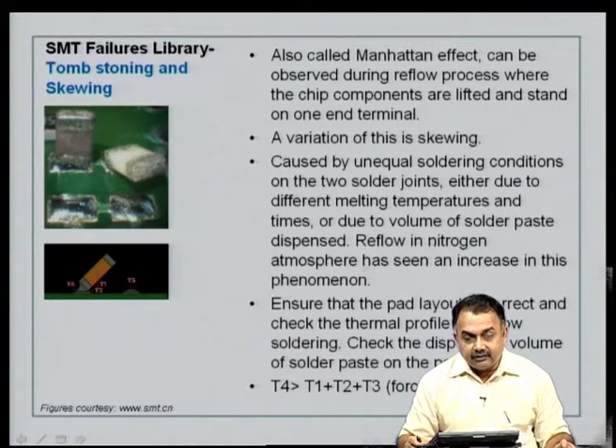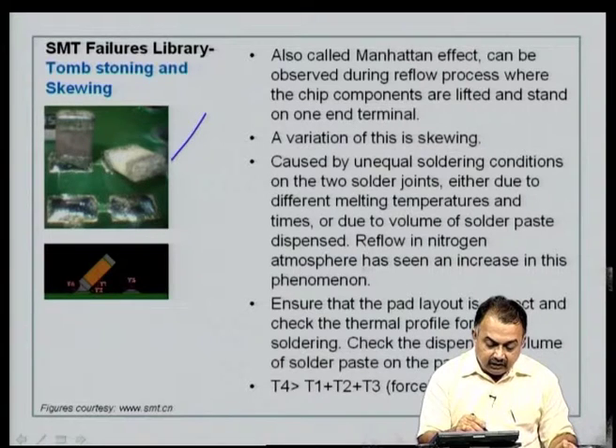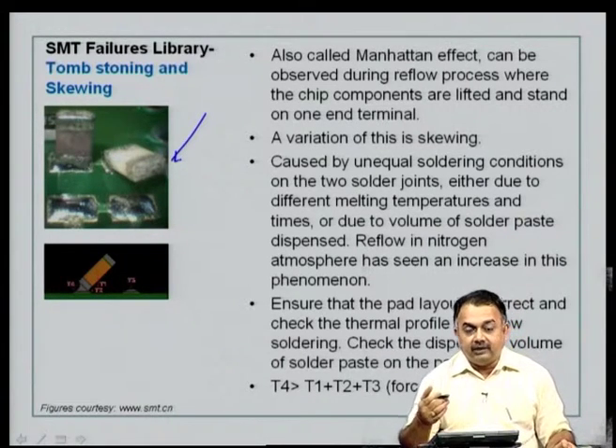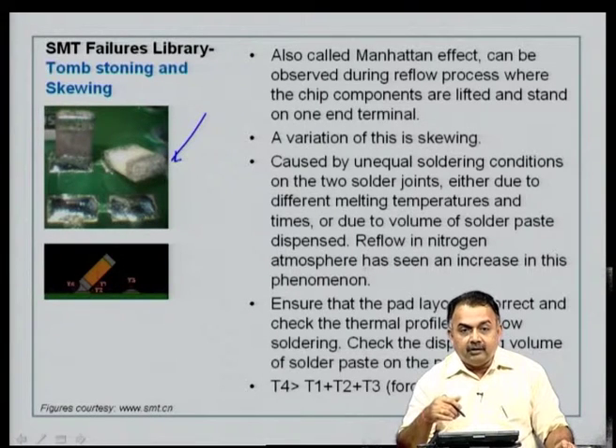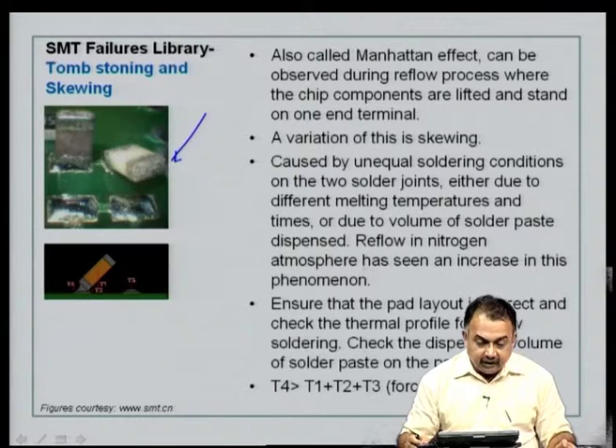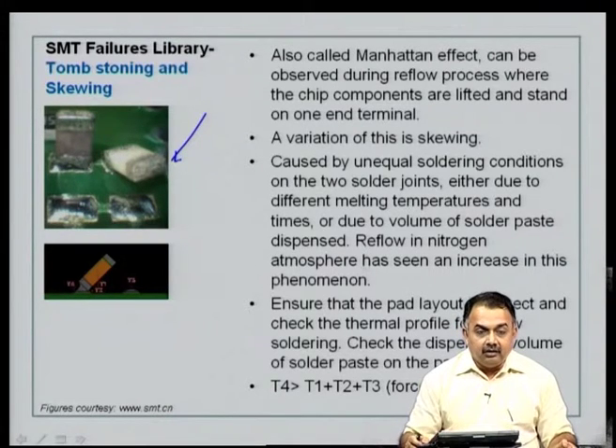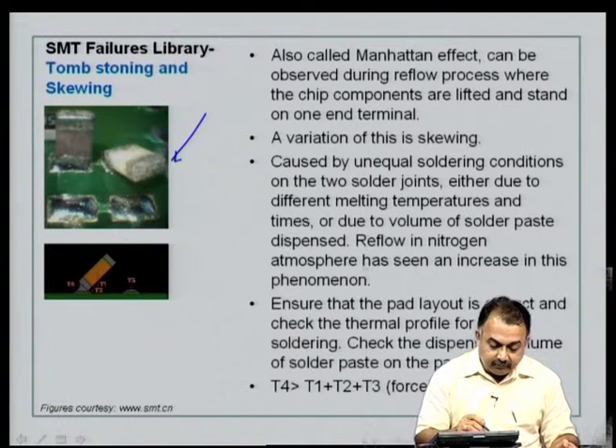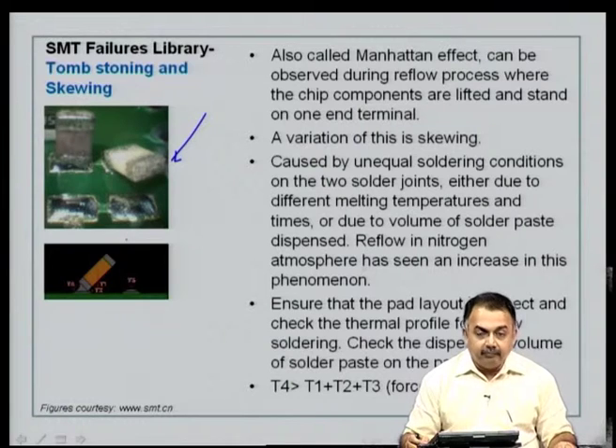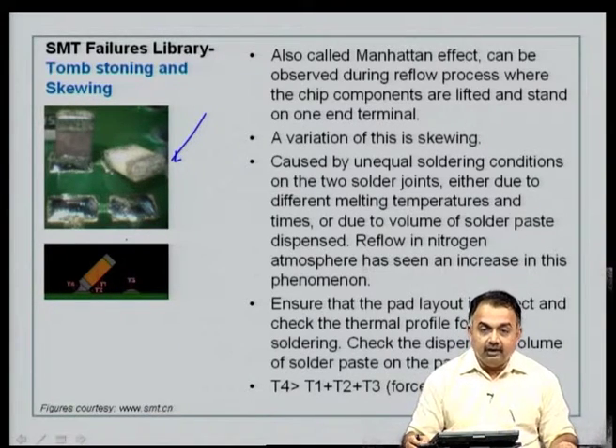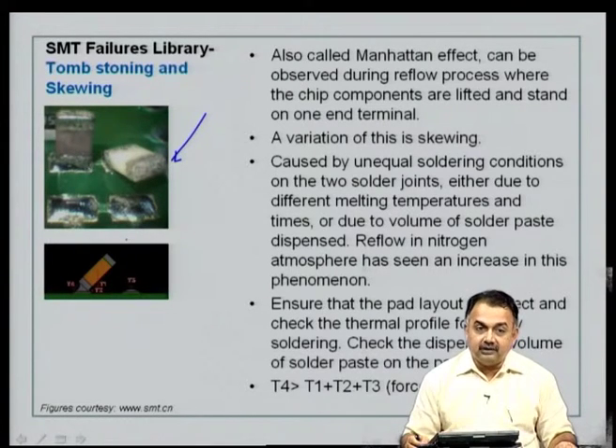We have seen an exhaustive list of the failures library in that particular module. So, here this is basically to highlight the light weight of the components like your chip components that can have problems during reflow soldering, especially because the temperatures could be unequal at the different sites that you are seeing here in this picture of the chip component, or the material not being pure in terms of the components, and then the volume of the material that you have dispensed also could be unequal. And the other important issue is the atmosphere in which the reflow soldering process has taken place, either in air or in nitrogen atmosphere.